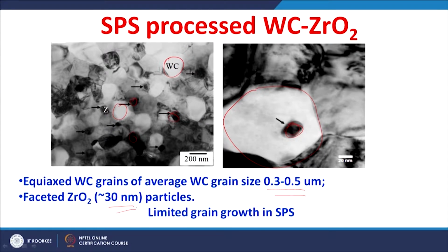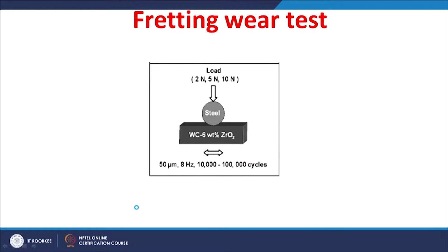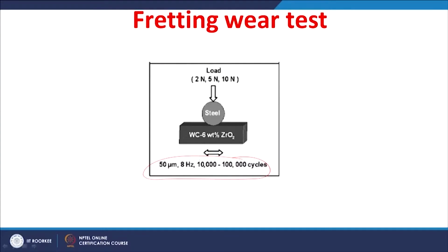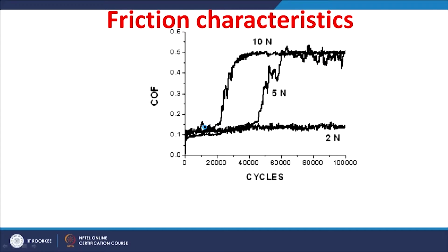There is only limited grain growth during spark plasma sintering, which gives a combination of superior properties. That is how we got a very high hardness of around 24 gigapascal and a moderate fracture toughness of around 6 MPa root meter. These tungsten carbide 6% zirconia ceramics were fretted against steel at different loading conditions with a fixed combination of fretting parameters. The fretting was done in mode 1 fretting conditions, which gave gross slip conditions at the contact. The fretting test parameters were fixed at 50 micrometer oscillation displacement with a frequency of 8 hertz, and the fretting was conducted with varied numbers of cycles, from 10,000 to 100,000 cycles.